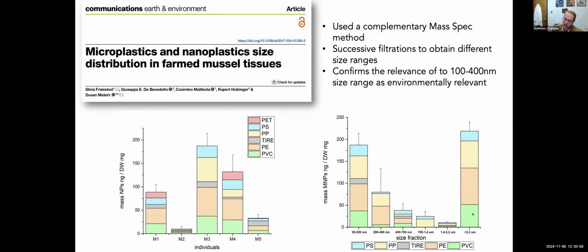But what they're showing is using a different mass spec technique. They use thermal desorption, proton transfer reaction mass spec. And they're still showing that polyethylene is by far the dominant polymer that they see, followed by polypropylene and a little bit of polystyrene and PET. Concentrations they're seeing in muscles are very comparable to what we are showing in human placentas and a lot of other tissues, about 100 micrograms per gram.